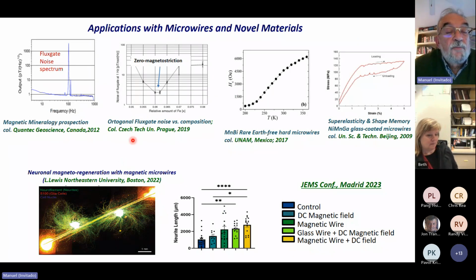We have been collaborating with different companies and technical universities. For example, making use of non-magnetostrictive microwires as sensing elements for orthogonal fluxgates. Also, in collaboration with visiting scientists from different countries, this one from Mexico, we were able to prepare by this rapid solidification technique rare earth-free manganese bismuth microwires. And here the coercivity is not so large, but the important thing is that it increases with the temperature. Or also we were able to prepare superelastic microwires of nickel, manganese, gallium with shape memory properties also.